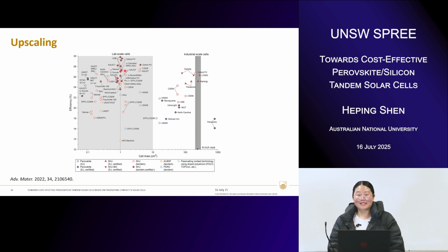And the final aspect, I will very briefly touch on the upscaling. This is an image from a review paper on tandem, to summarize the performance of the perovskite silicon tandem on different sizes, as you can see, sizes from 0.1 square centimeter to 1, 10, 100 square centimeters. So there are two gaps here.